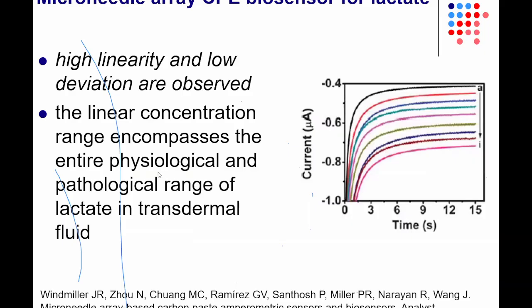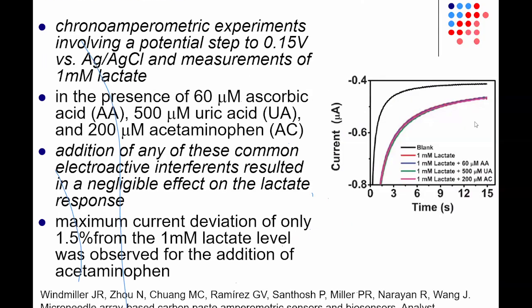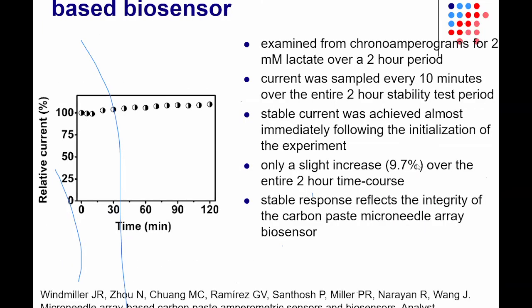And here you can see that you can detect lactate in the physiologic range with this sort of electrode. Here you can see the detection of lactate in the presence of interfering molecules like ascorbic acid, uric acid, and acetaminophen. And you can see here that you have a negligible effect on the response of lactate. Here you can see good stability of the biosensor. So you can see here a stable current, a slight increase in the current over a 2-hour time course.